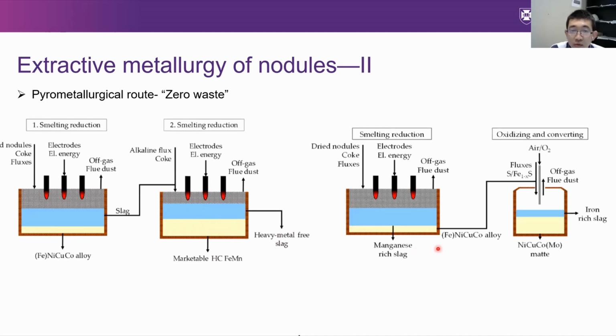Another product is also the manganese rich slag and the iron nickel copper alloy. This alloy is introduced to the converter for refining to remove most manganese and iron by blowing oxygen, and then sulfur is added to produce this nickel copper cobalt matte. So it's a different product for metals.